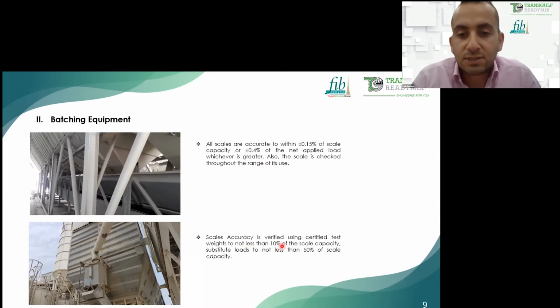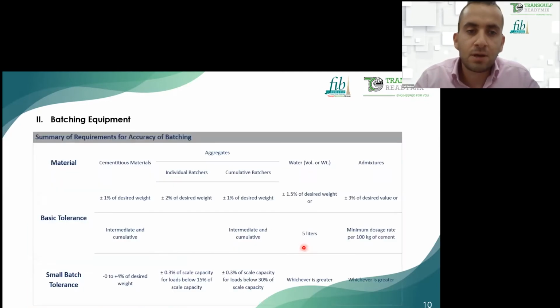And scales' accuracy is verified using certified weights, not less than 10% of the scale capacity. As an example, if the scale capacity is 5 tons, the certified test weight must be 10% of 5,000, which is 500 kg, and must be used during the calibration. This is even included in this scheme.